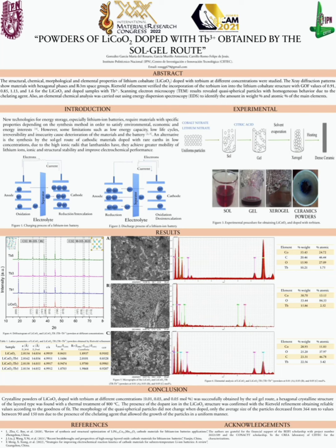Crystalline powders of lithium cobaltate doped with terbium at different concentrations, 0.01, 0.03, and 0.05 mol%, were successfully obtained by the sol-gel route. A hexagonal crystalline structure of the layer type was found with a thermal treatment of 800 degrees. The presence of the dopant ion in the lithium cobaltate structure was confirmed, as the Rietveld refinement obtained reliable values according to the goodness of fit.